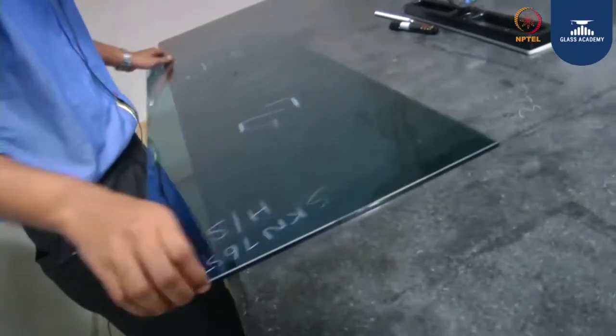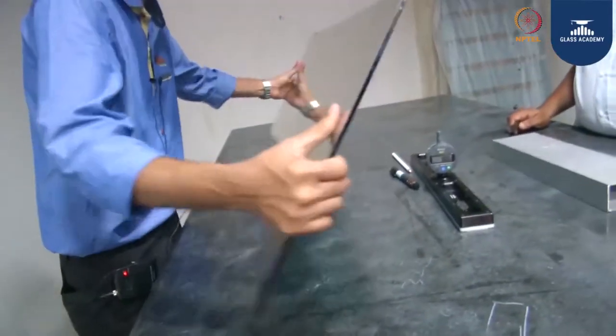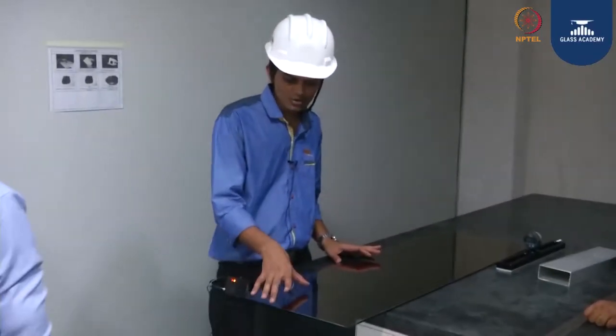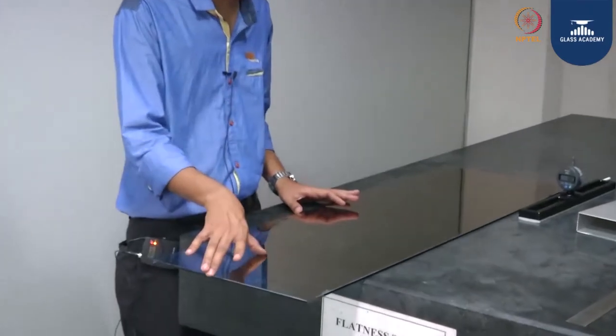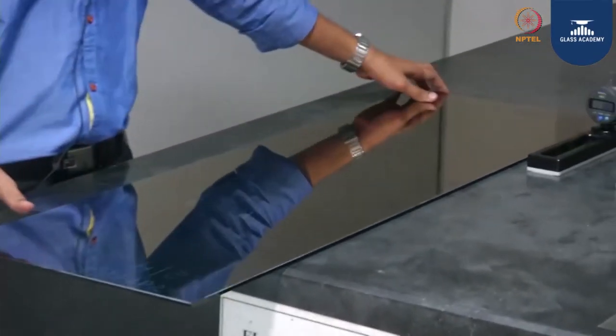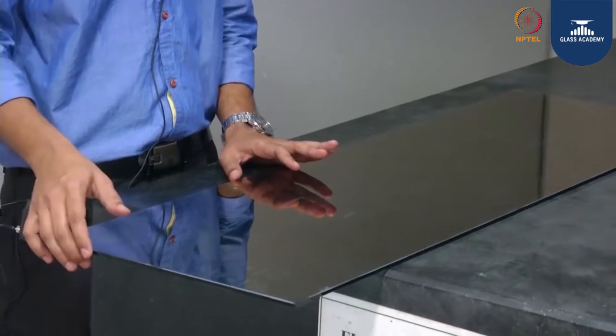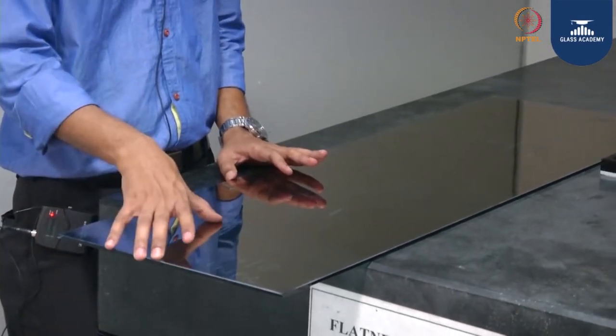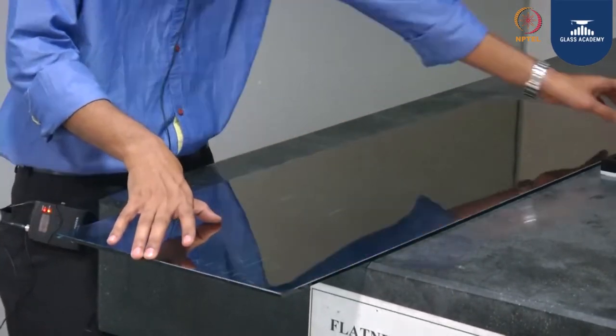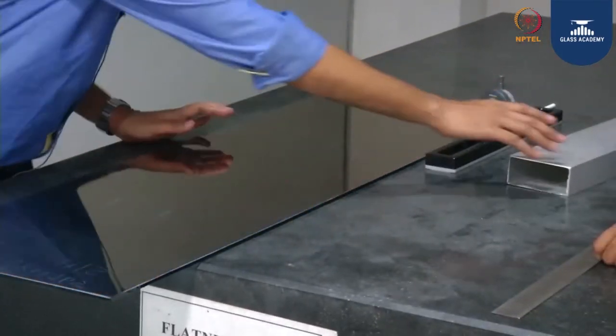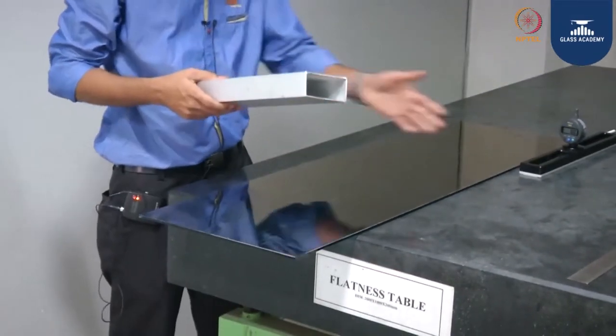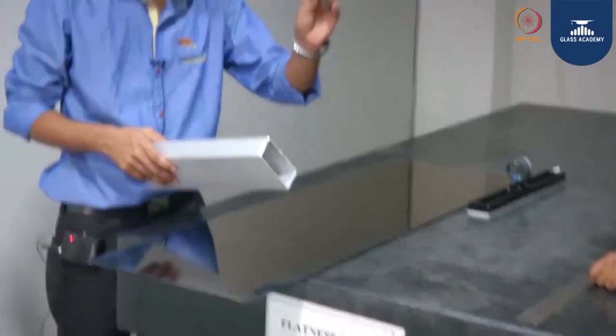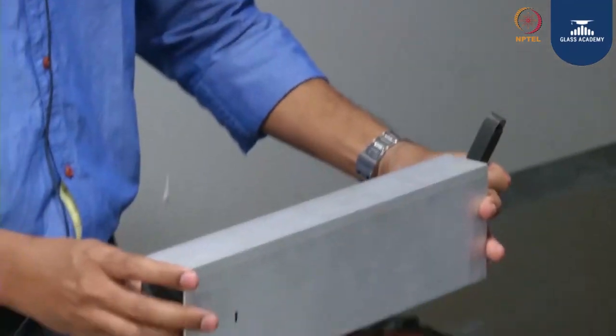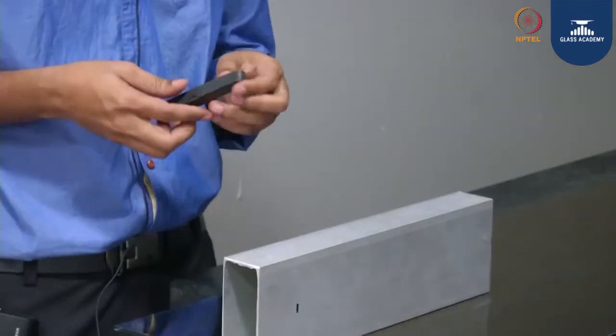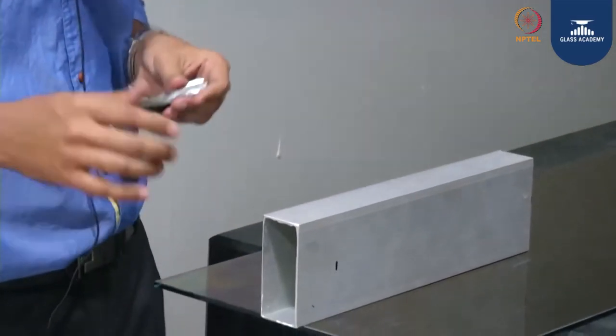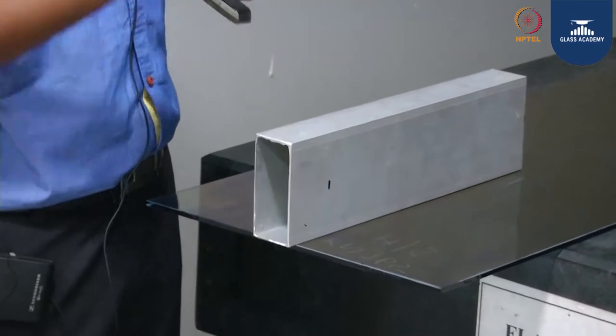mm. Now we are going to see the second test, that is known as edge lift or edge dip. The process for this one is, first we need to hang 150 mm on the flat surface. Next, we need to take a straight edge and a feeler gauge. We need to keep the straight edge vertically and insert the feeler gauges. We need to make sure the coating is on top.